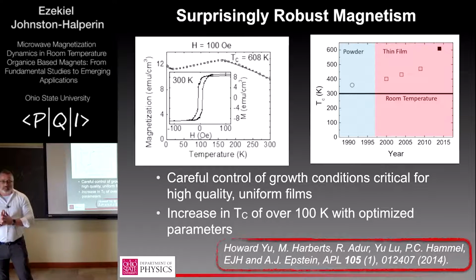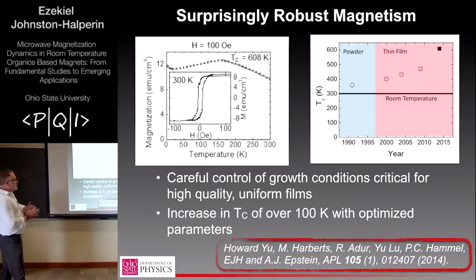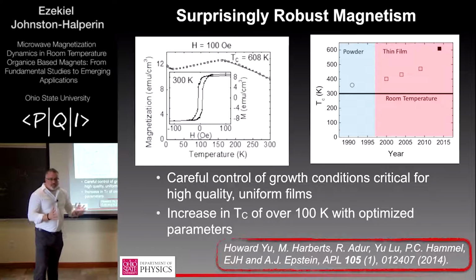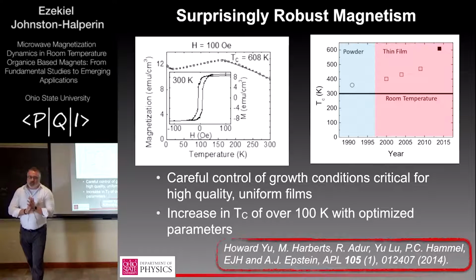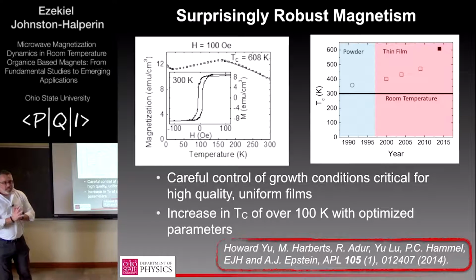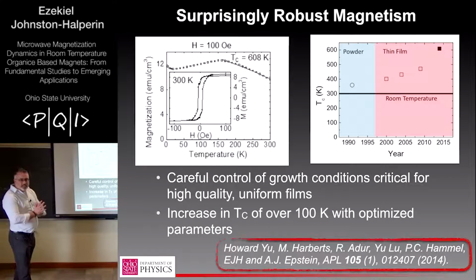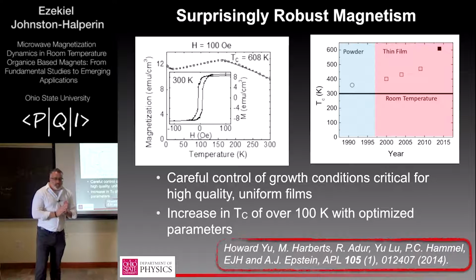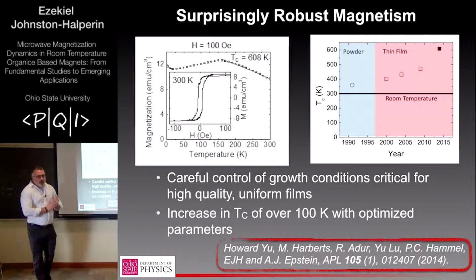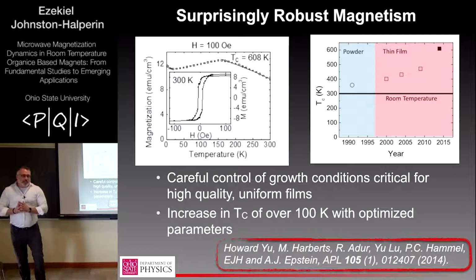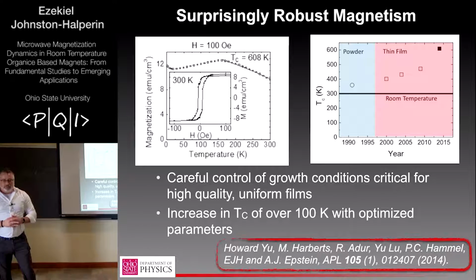Yeah. How thick are the thin films? Our typical growth is about 200 to 300 nanometers. We've grown as low as 50 nanometers and as thick as 10 microns. Okay. We haven't had any particular reason to make it thin. Making it thick makes some of the properties better, which I'll get to in a bit.